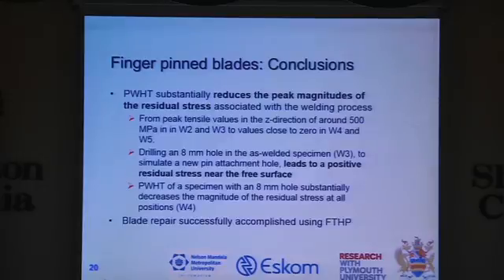From peak tensile values in the Z direction of about 500, we went to very low values. By drilling the hole, once you've drilled the hole, you end up with this positive residual stress. Tensile residual stress is on the inside of the hole, but they're of the magnitude of about 40 MPa. So you're going to have to realize that you sit there with the tensile residual stress that you have to deal with in some other way.